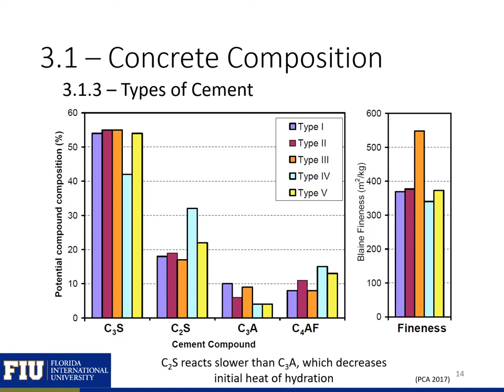Type 2 and 5 cements, which are sulfate resisting cements, have lower C3A contents. C3A is one of the reactants in external sulfate attack, so limiting C3A content reduces susceptibility to external sulfate attack. Type 3 cement, or high early strength cement, has a much higher fineness than the other types of cement, which means the cement will react faster, leading to a higher heat of hydration and higher early strength development.